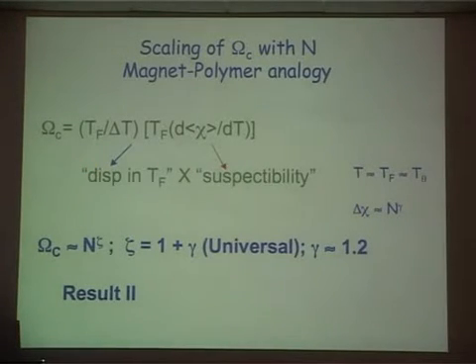So we check this out. Now what is this dimensionless quantity? It is just equal to the melting temperature squared times the height of the derivative of this order parameter with respect to temperature at Tm, divided by the width of the transition. That's what this is, and this is dimensionless. The reason we constructed this dimensionless function is that you could compare simulations and experiments done either by changing temperature, guanidinium, or even force on equal footing. Very easily you can see that if the transition was infinitely cooperative, as it would be in an infinite system, this would go to infinity, whereas if it were not, then it will be small. And so with this definition, we are good to go.